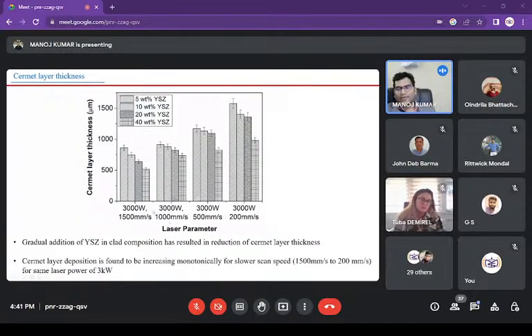So we find that when we increase the laser power or laser input energy, the deposition will increase, of course. So this is the scan speed, so how fast you are moving the laser beam. If your movement is very fast, that means the laser is interacting for less time with the materials. So laser input is less, energy input is less, so deposition will be smaller. So the way we are decreasing the scanning speed, deposition is increasing.